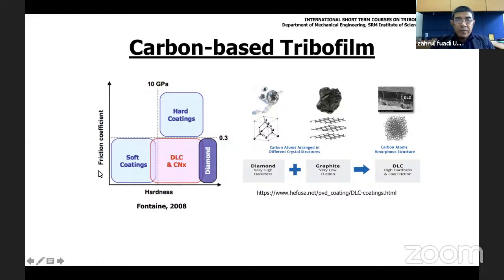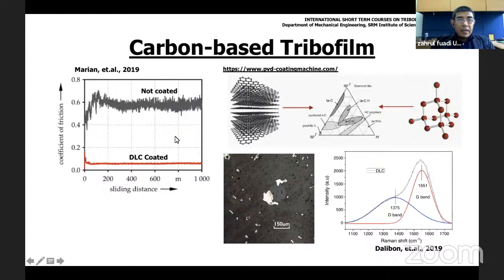So by using an additive, we can have a tribofilm, which is sometimes in the structure of carbon base, but we can also produce the carbon-based tribofilm on the surface before the friction. And this shows the friction curve of two friction pairs. The first one is uncoated steel, and the second one is DLC coated. We can see that with DLC coating, the friction has reduced by a factor of 3, from 0.6 to less than 0.1.